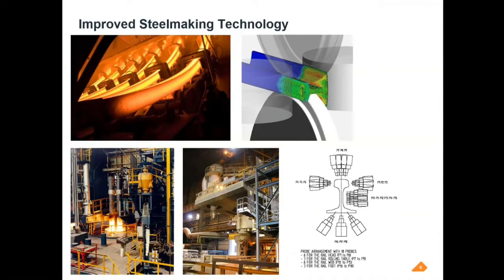But also the tolerances have got tighter as well. So rails, let me give you an example. Structural sections, 203 by 203 millimeter universal columns. The flange length tolerance today is plus 4 millimeters, minus 2 millimeters. So I've got a 6 millimeter tolerance range to work within, and I've got a compliant section. Rails, by comparison, is plus or minus 0.5 millimeters on the rail height dimension from the top of the head to the bottom of the foot. So it's an order of magnitude tighter tolerances for dimensions.